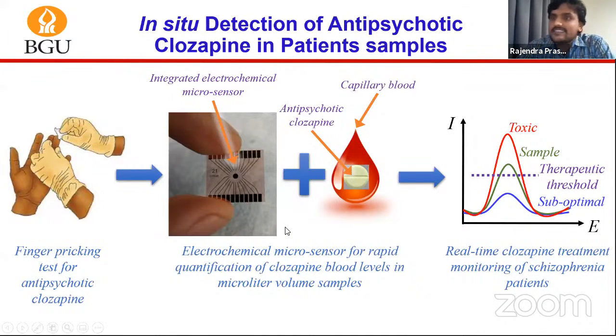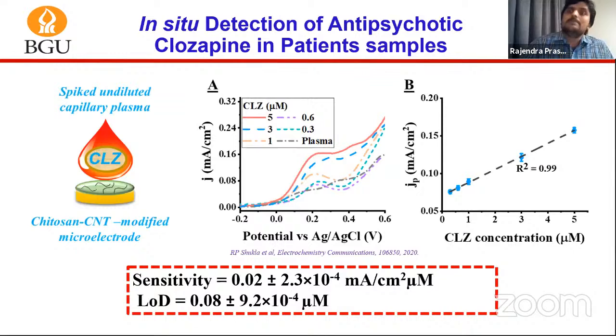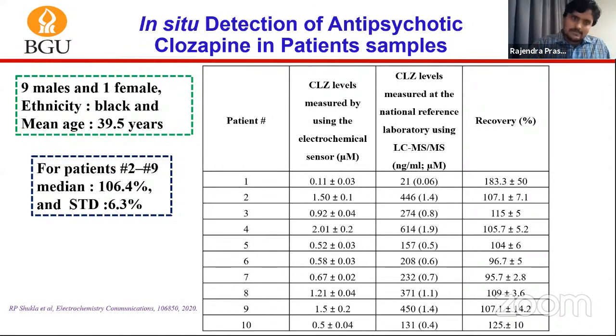Later on, we also tested the performance of our developed microelectrode modified with carbon nanotube for the detection of clozapine levels in patient samples. What we basically did, we took the patient sample before the treatment, before giving clozapine, and after 2 months of the clozapine dose, we also took samples. The samples without clozapine were used to make this dose response plot, and then the samples after 2 months of the clozapine dose were used to recover using this dose response plot. We selected basically 10 patient samples, with 9 males and 1 female, with an average age of 39.5 years.